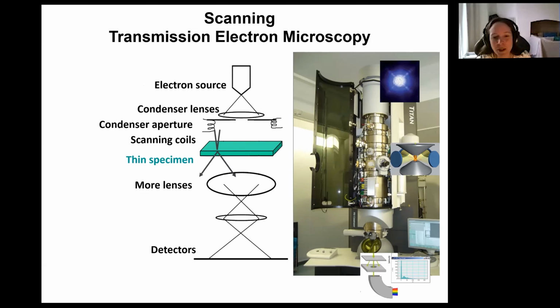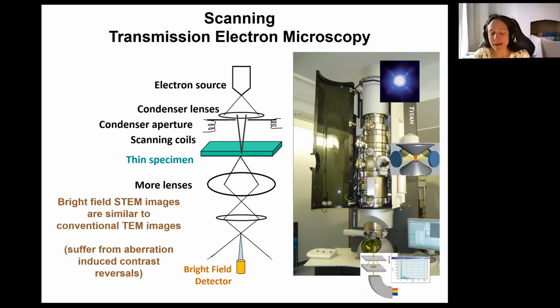So in the scanning mode, we have a very finely focused probe, and we can focus that electron beam down to a sub-angstrom diameter, and we can then scan it across the sample. And we build up the image pixel by pixel, so we get individual information at every pixel as the probe is scanned across that surface. Now, the imaging mode that is most like the transmission electron microscope is called bright field scanning TEM. And the bright field imaging mode is very powerful, much like a TEM image where there's a vacuum or no specimen, it'll be bright, and where there's a specimen, it appears dark.